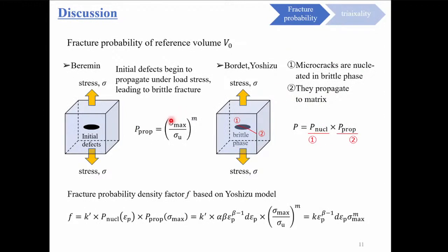the Beremin model assumes an initial defect and considers only stress-induced crack propagation, while the Bordet model considers the probability of small cracks in the brittle phase due to plastic deformation. In the Bordet model, the cumulative probability of crack initiation is linearly related to the equivalent plastic strain, but this is modified in Yoshizu model by considering it as an exponent of beta.